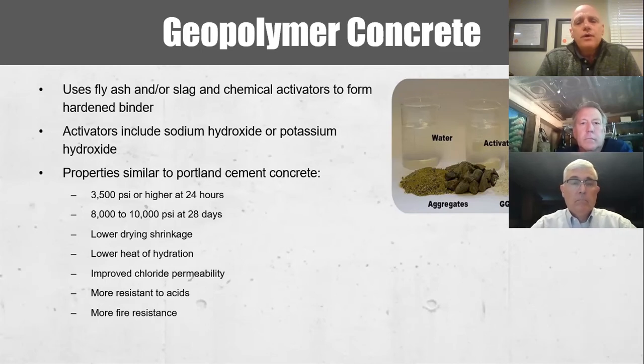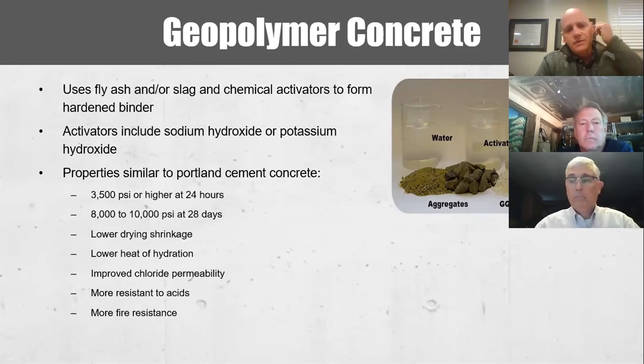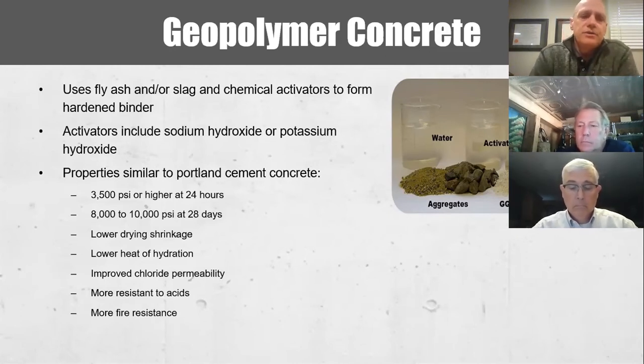But creating demand for it will result in more use and the cost of the construction or that material coming down somewhat. The activators include sodium hydroxide or potassium hydroxide. Again, they're highly alkaline, which means they're caustic and hard to handle, expensive to make. That's what makes this concrete more expensive. But the properties are really favorable. So similar strengths, a little bit higher strengths generally than conventional concrete, but lower drying shrinkage, lower heat of hydration, and improved resistance to chemicals.